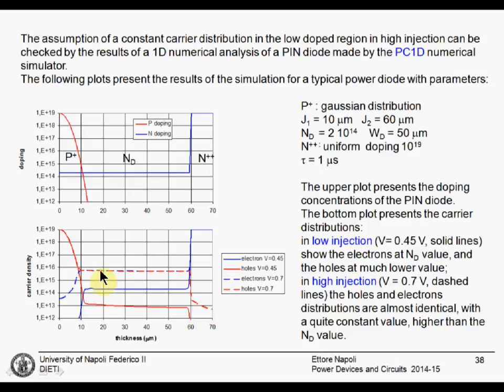But what is important to see is that the carrier concentrations here, n and p, are almost identical and much larger than ND. It's about 10 to 16 with respect to 10 to 14. Note how flat this carrier concentration is here. The lifetime is quite long, 1 microsecond, but not unrealistic. This is a realistic value.